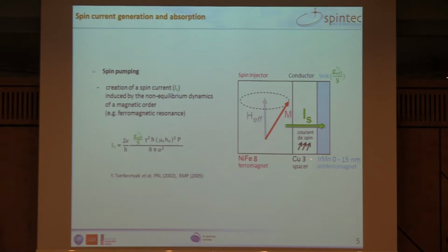So as it was said before, copper, as far as the spin current is concerned, will be quite transparent because the spin penetration lengths in copper are of the order of hundreds of nanometers or even microns. And here we are using a spacer of 3 nanometers. So basically we put our nickel iron at resonance.